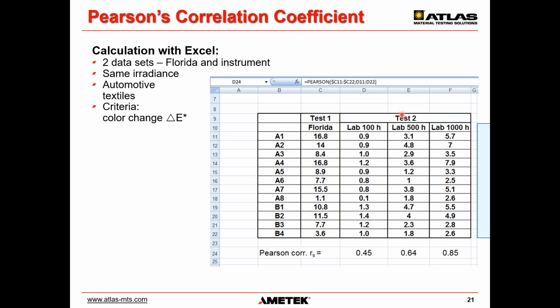And in Excel, it's relatively easy. You just have to type in a cell that it's equal to Pearson. Then you have to include the first data set. So here from Florida, 16.8 to 3.6, so cells C11 to C22, followed by the second set of data. In this example, that's the lab weathering results after 100 hours, from D11 to D22. Then you just close the equation, press enter, and the program automatically calculates the Pearson correlation coefficient. And it's 0.45, so not a really good correlation, I would say.